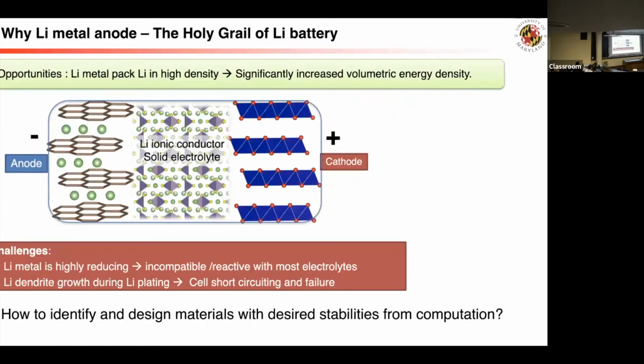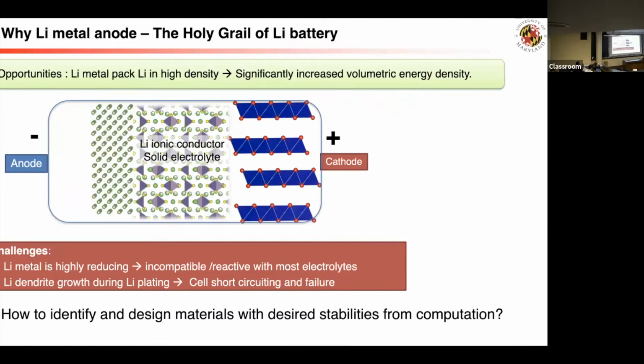Okay, so with that, I will move to the second part of my talk, which is material stability. Because as we talked about at the beginning, one thing with the solid electrolyte is the ionic conductivity. Another thing is stability, because one big topic in batteries nowadays is using lithium metal to replace graphite. You can see lithium metal can pack lithium so densely, so that's a way to significantly improve the energy density of the battery.